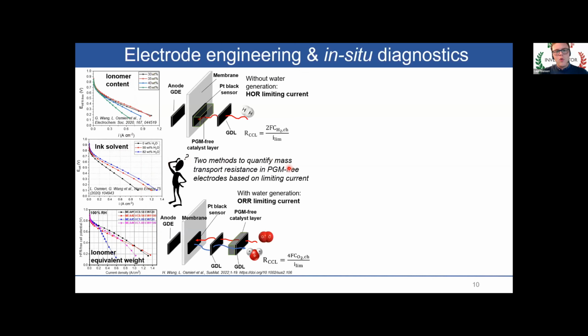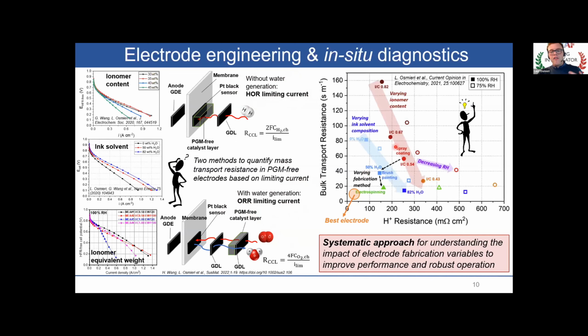I developed two methods to quantify the mass transport resistance in these PGM-free electrodes based on the limiting current measurements, one based on hydrogen oxidation limiting current that does not consider the generation of water, and another method a little bit more complex based on oxygen reduction reaction limiting current, which considers the generation of the water within the electrode.